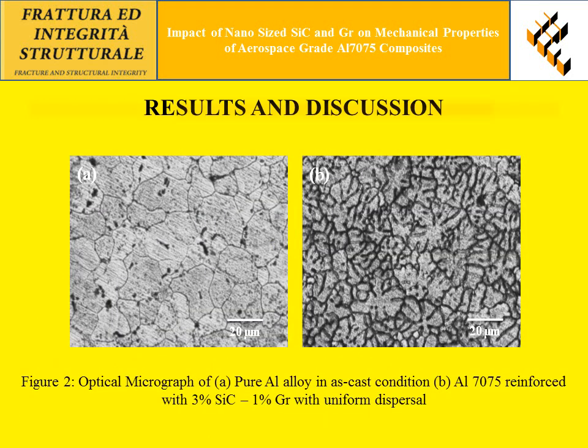The figure shows the microstructure study of base material and hybrid Metal Matrix composites. From the figure, it is observed that the grains around the hard reinforcement are much finer when compared to the grains around the reinforcement free matrix alloy. So, hard particulates can induce the recrystallization of aluminum alloy by accelerating the particulates nucleation among the matrix and reinforcement phases.